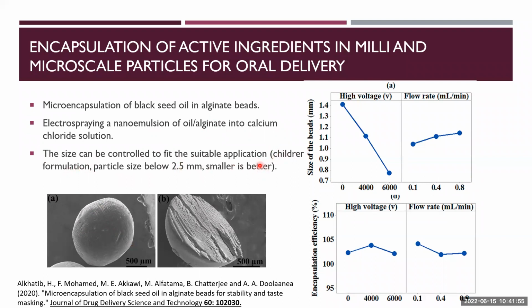Then we can actually control the size using the flow and voltage. We don't need to change the formulation. So usually we use factorial design to find the suitable combination of voltage and flow rate. You can see when we increase the voltage from 0 to 4,000 to 6,000, the size goes down from 1.4 millimeter to 0.8 or 0.7 millimeter.